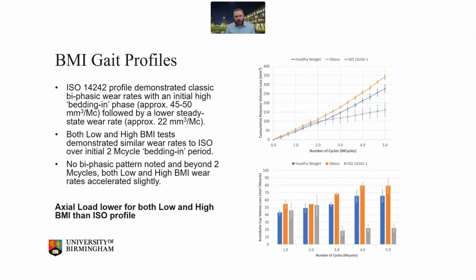Typically, it's commonly accepted knowledge in hip simulation that when you increase that axial load, you'll typically increase wear as well. By introducing the kinematics, we actually brought that axial force down, but still had an overall higher wear rate once we had fully determined that we were in steady state. And then we saw slight differences between the healthy weight and the obese profile.